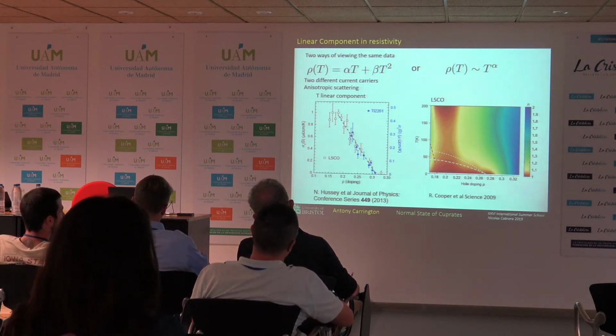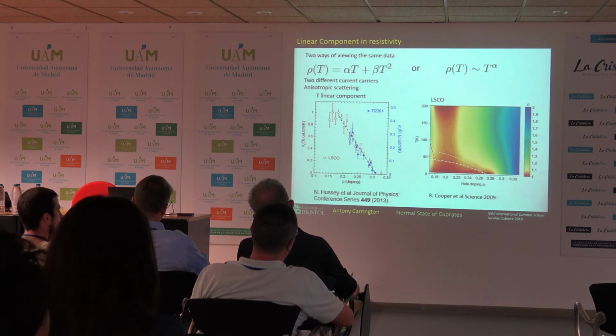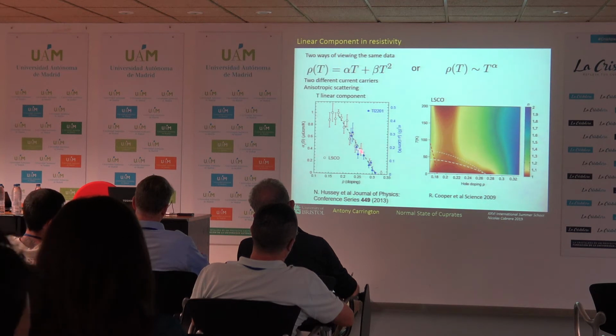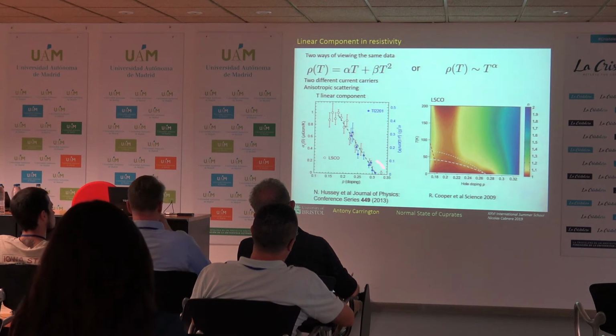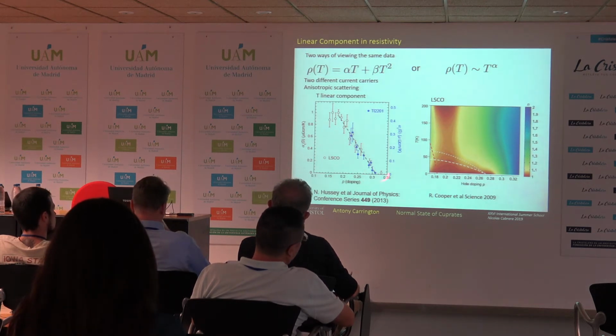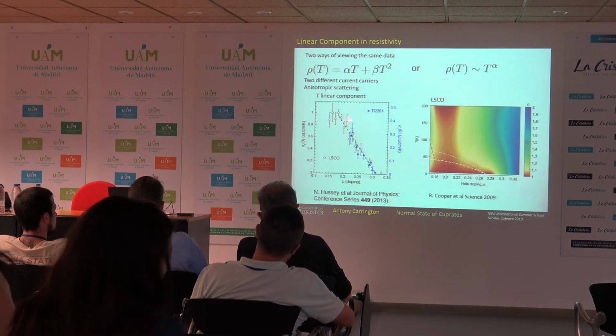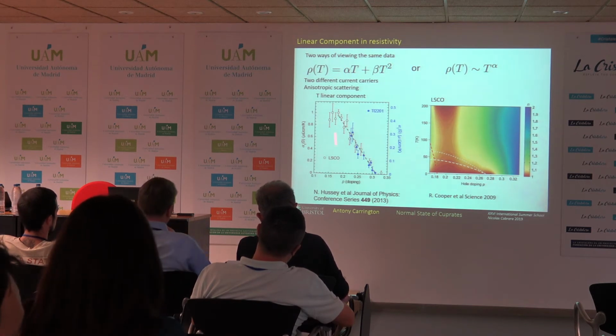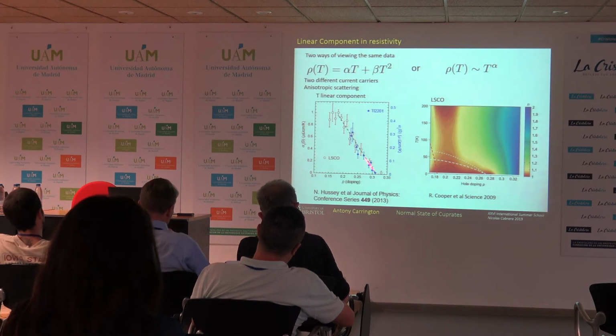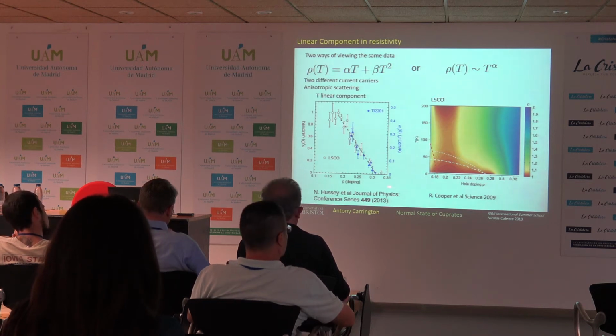So if you look at the same data in this way, and you look at the size of this linear term, what you find is that the linear term goes to 0 pretty much right at the edge of the superconducting dome, at a doping of about 0.3, and it increases to a maximum value at optimal doping. So it's as though this linear term correlates with the superconductivity. The emergence of the linear term in the resistivity correlates with the emergence of superconductivity.